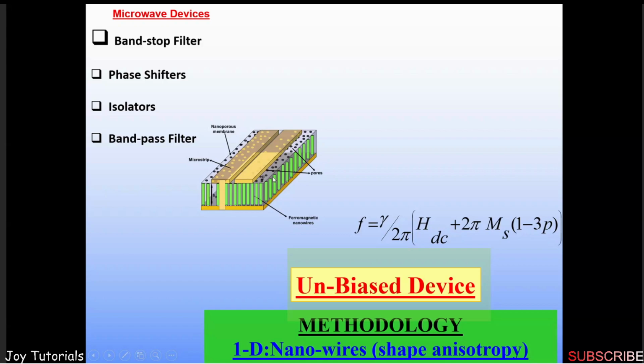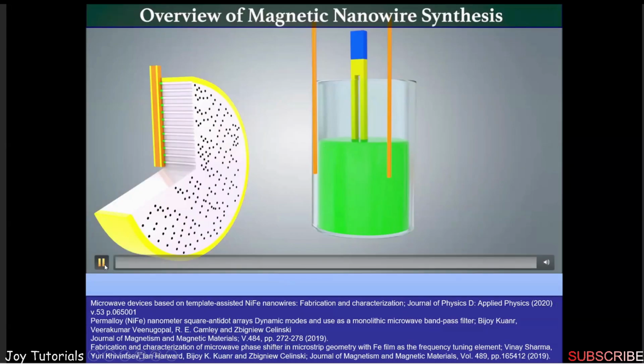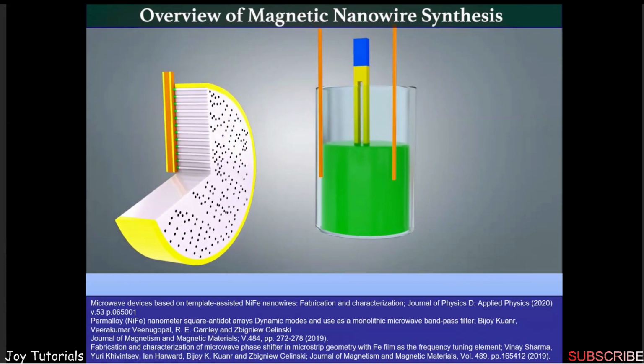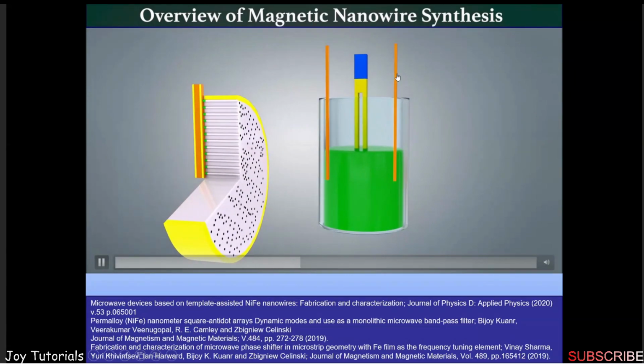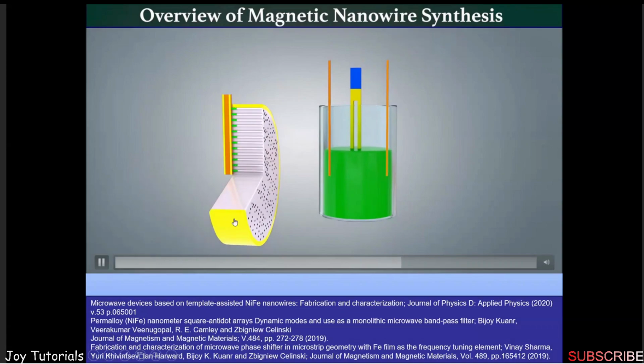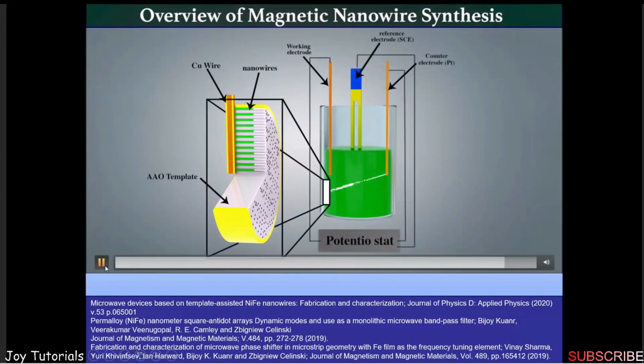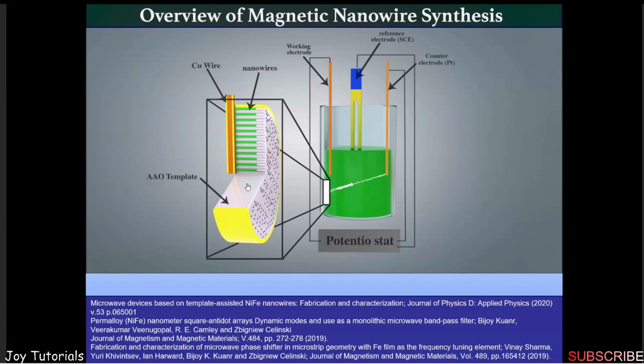Now, to grow the nanowire, this is a very simple technique. One can do this through electrodeposition. This is an electrodeposition cell. It's a three electrode electrodeposition cell, where the material is deposited on the template. When we put the template on the working electrode, having the counter electrode or the reference electrode is to maintain the voltage so that we can have a uniform growth, and then we can have the magnetic layers inside as wires. The diameter of the wires, we design from 20 nanometers to something around 200 nanometers, depending upon the frequency of operation. It's a very simple technique, very cost-effective, very cheap, just an electrode system, nothing else.